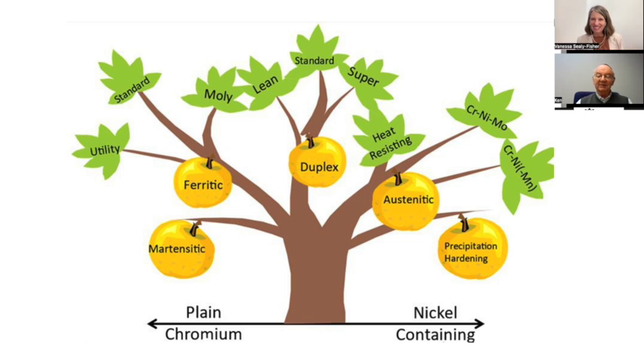Point out that on the nickel side, we've also got some alloys which are referred to as precipitation hardening alloys. And this is the fifth branch. It's perhaps the Cinderella branch in the sense that it's not well known and not widely used, but yet it's the branch that can perhaps offer the highest strength in the stainless steel range. And that is achieved by forming a precipitate in the material, and the whole technology associated with that requires an additional heat treatment operation to develop that strength. So they also have moderate corrosion resistance, but as I mentioned, their usefulness stems from their strength and also their toughness. So it's not strength with brittleness, but strength with toughness.